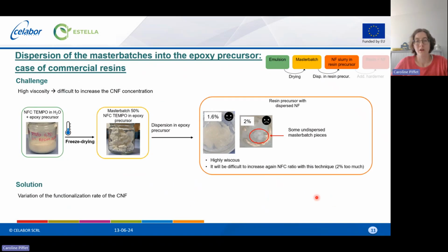So we started our development with commercial resins, and the first challenge we have to face is the high viscosity of the media. So you can see here what the emulsion looks like. Then after the freeze drying, we have the master batch looking like this. And when we disperse this into the precursor, so the precursor is the same that is already included into the master batch, of course, we achieve to disperse around 1.5%, but this is not the concentration that we will have into the resin because you still have to add the hardener.